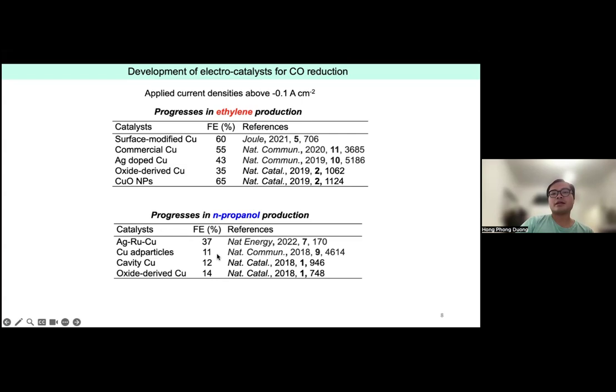Okay, to adapt to industrial applications, there was some techno-economic analysis showing that you need to achieve the reaction at least 0.1 ampere per square centimeter. This is the applied current density. And the Faraday efficiency should be at least 70% for a product to make it practical. And also the durability of the system should be over 1,000 hours. And the last thing is that the total cell voltage should be lower than 3 volts to make it economical. But today I will just talk about the Faraday efficiency, and the other points.